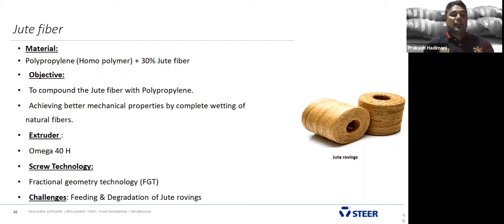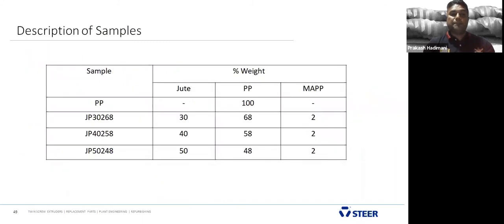Also, it gives higher mechanical properties compared to even wood. We observed higher tensile strength; jute is going to give that with the long jute, not the chopped jute. It's a long, twisted jute. And we conducted trials with 30%, 40% and 50% jute. We have used a homopolymer polypropylene, and also a coupling agent, constant for all the systems.